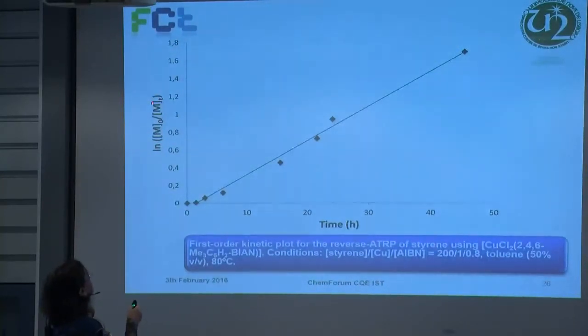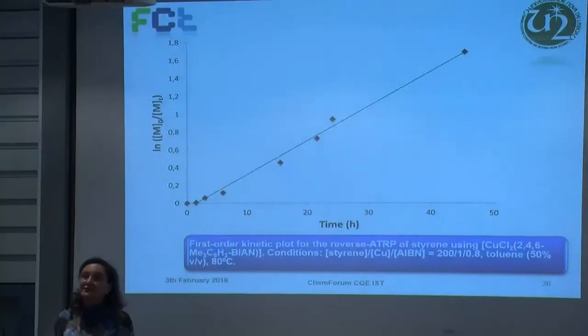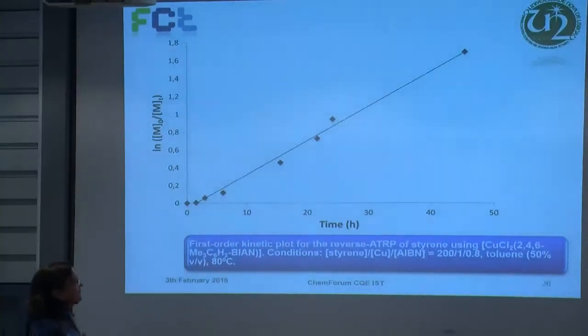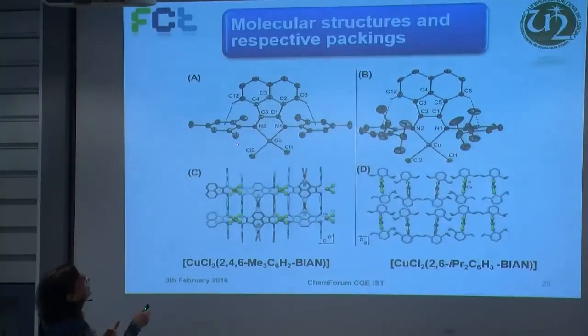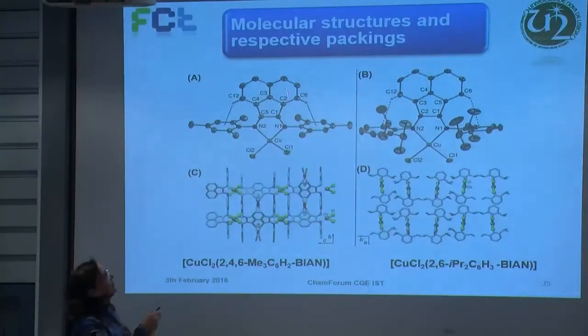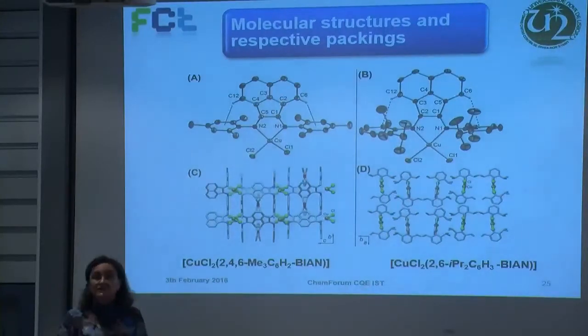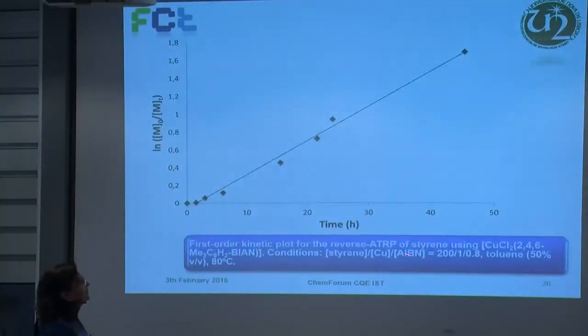For instance, representing ln of M0 over Mt, we got a straight line. That means that it's a first-order kinetic, which means that there is always a constant concentration of radical in solution, which is in favor of the reverse ATRP mechanism for the polymerization. This was done using this catalyst, the trimethyl, because it was the one found to be active for this kind of catalysis. This other compound was not so good, so it was discarded, and we continued with the trimethyl.